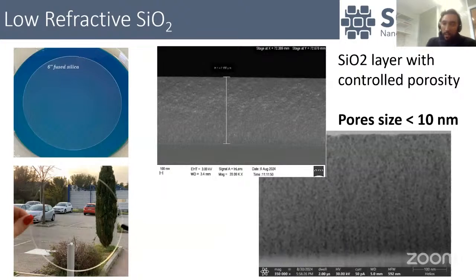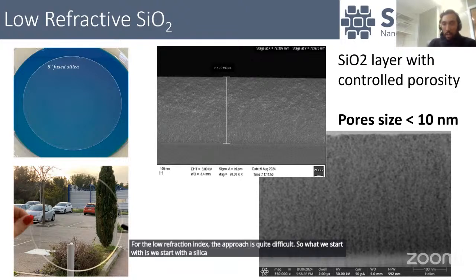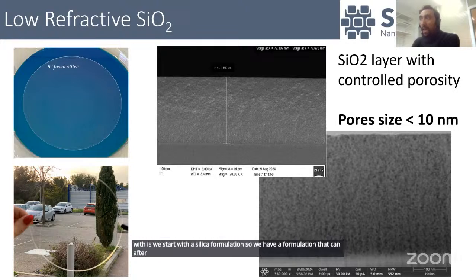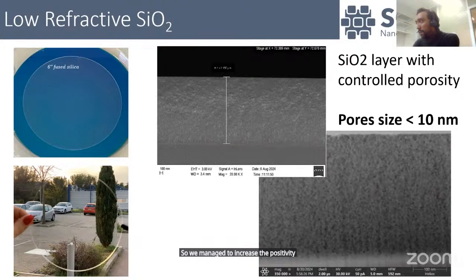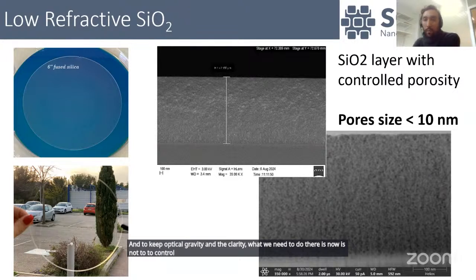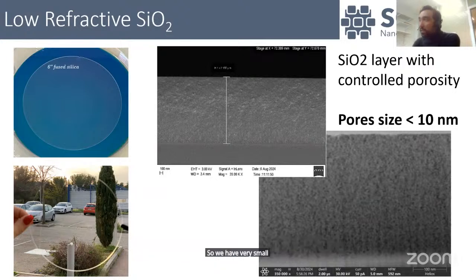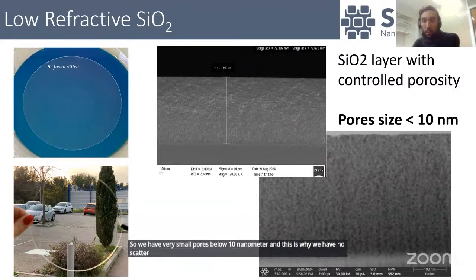For the low refractive index, the approach is quite different. We start with a silica formulation that can, after curing, become pure glass. And what we did is that we managed to control the porosity of this layer. We managed to increase the porosity up to 75%, which allows us to reduce the refractive index down to 1.12. And to keep the optical quality and clarity, what we need to do there, not to control the crystal size like we did for TiO2, is now to control the size of the pores. So we have very small pores below 10 nanometer, and this is why we have no scattering or absorption, because the pores are very small.